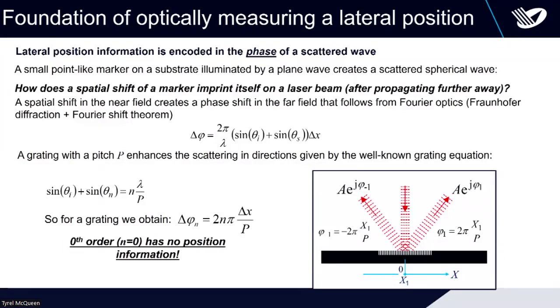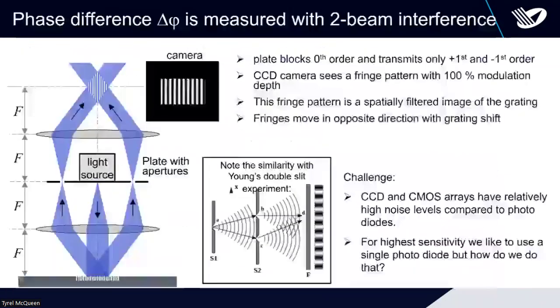So how does it look here? That's an illustration of the incoming wave on an alignment grating, and we get a plus and a minus first diffraction order. And the lines represent the maxima of the electric field. And that's our alignment grating. So if we shift that in X, then what will happen? You get a phase shift of these beams in the first and minus first diffraction order. So there you can directly see you get an encoding of the position into the phase. So we need to measure that.